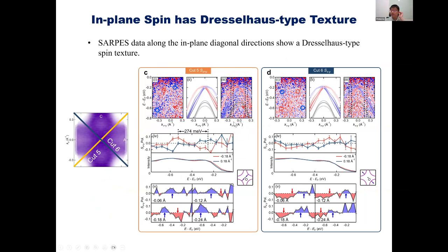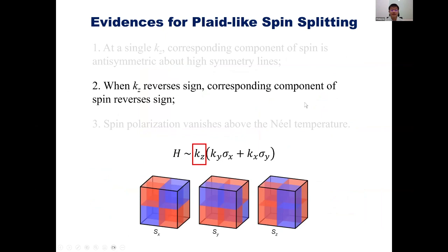So basically, it confirms that the in-plane spin has a Dresselhaus-type texture. The second evidence for the plate-like spin splitting is this part of the Hamiltonian, which means that if we change the sign of Kz, the entire spin will change. We can see from this cartoon that if we change to Kz less than 0, the red spin will become blue and the blue spin will become red.